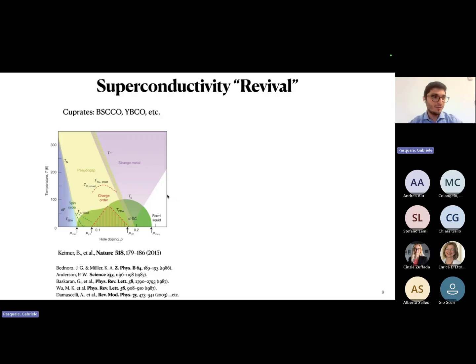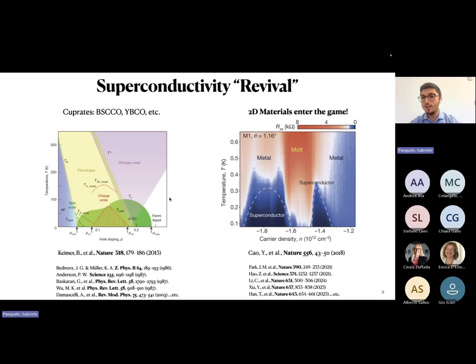However, superconductivity witnessed a revival in 2018 when 2D materials entered the game. It turns out that if you twist two layers of graphene to a specific angle, which is called the magic angle, you recover a superconducting transition. And not only do you have superconductivity, but you can control the different phases with gate voltage.